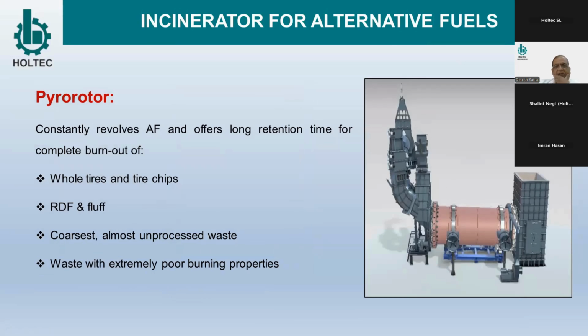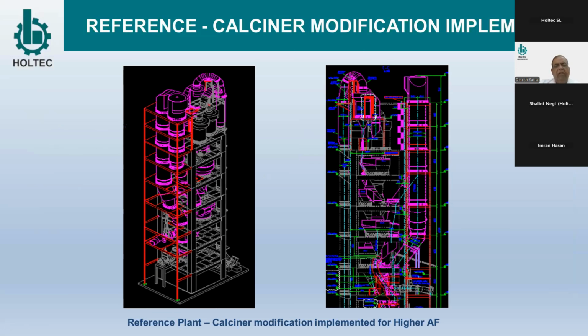Now, when we talk of higher alternate fuel usage, a few technologies are coming up and are available in the market. One important point is that the calciner also plays a major role. Most of the places you find the calciner is not suitable for higher capacity, higher AF usage. So Holtec has done this at many places, where we have modified the calciner. The residence time has to go up to at least 5 seconds minimum. If no option is available, at least we have to put up a new calciner completely, take out the duct, and bring it back into the system, as an independently supported system. So this is an important modification, which is required when we talk of higher AF feeding, higher percentage TSR.